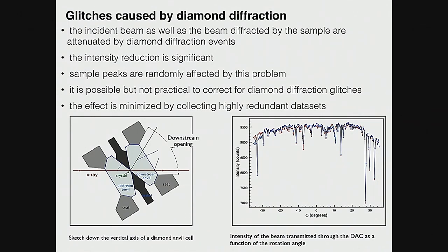Your incident beam and diffracted beam will be diffracted by diamond, taking away part of that strong beam. And it's not impossible in theory to deal with it. You can calculate the orientation matrix of your crystals and the diamond. But of course, diamonds also change under pressure. The peak shape will change. It's difficult to deal with. You can rotate your diamond anvil cell and collect the same peak, and so soon enough peaks will have this effect coming in and out, and so you can average them all, and your average will be more robust than a single measurement.